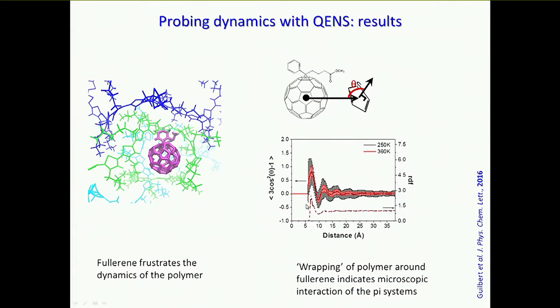And we could do this by looking at the effective radial distribution function for that angle, a kind of order parameter for the cofaciality of thiophene relative to fullerene, and we could see there seems to be an interaction. So to put it into simple language, the pi-conjugated part of the polymer is wrapping around the fullerene. So there is a specific chemical interaction which makes sense of the fact that the amorphous part of the polymer is frustrated, slowed down by the presence of a fullerene in the blend.